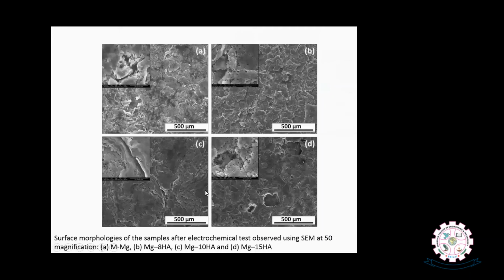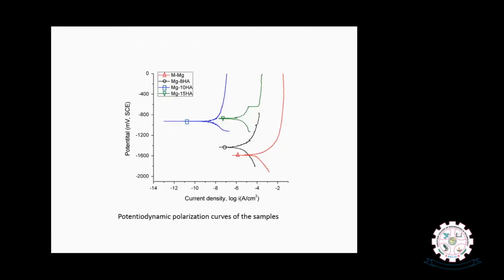And the corresponding composites were subjected to corrosion, and then the sample surfaces were investigated and compared with the composites, where magnesium has undergone higher degradation with numerous cracks. And the electrochemical test also confirmed that among all the compositions, the 8% and 10% composites have shown a lower amount of corrosion. The composites made through ball milling help improve the magnesium's mechanical properties as well as corrosion properties, as shown here.